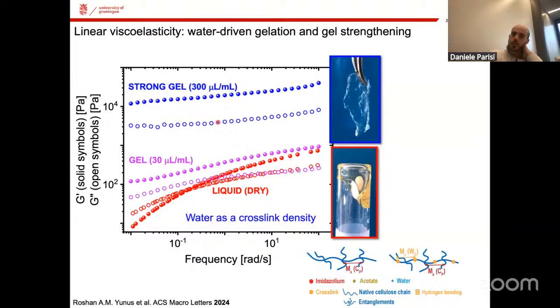And in fact, as you add more and more water, the gel becomes much stronger. Just by increasing the amount of water by 1 order of magnitude, the modulus increases by 2 orders of magnitude, from 100 Pascal to 10,000 Pascal. So you can regulate the elasticity of the system in an elegant way just by adding water, which is counterintuitive for many jelly systems.